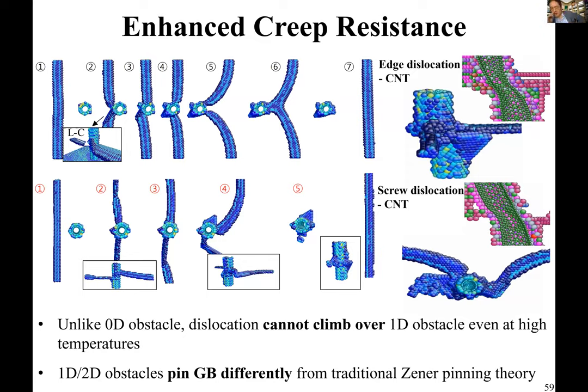Another very interesting thing is that these materials harden not only the room temperature tensile strength, but also the high temperature creep strength, which is what we need for nuclear materials. So creep basically means, let's say at 70% of the room temperature yield strength, it doesn't yield right away, but you wait a long time with that load on as a dead load and you have patience. So what we found is that unlike traditional precipitate hardening, where you have particles that stop dislocations, the dislocation can just wait for vacancies and climb over these precipitates, if you have time and temperature and patience, so they would creep over them.